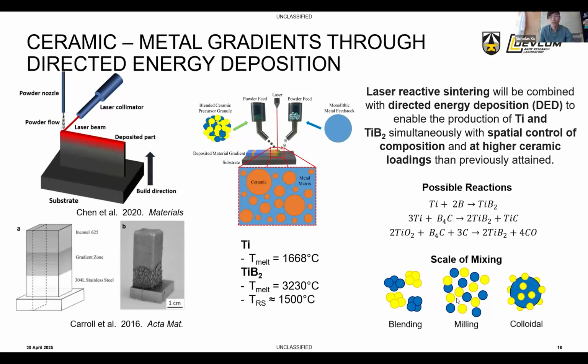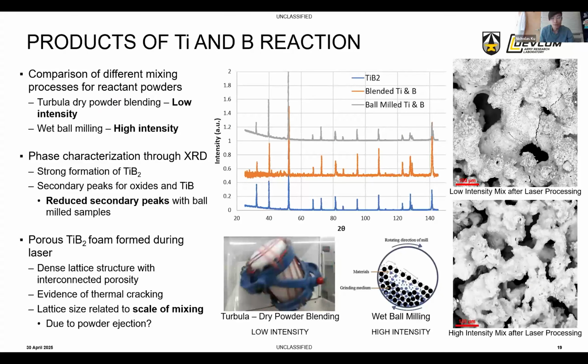One of the things that we're trying to figure out is how ceramic materials potentially react under a laser system. In this project, we were looking at using precursors, titanium and boron, which under a laser reacted to form titanium diboride, an advanced ceramic that we have some interest in. We did a lot of work on understanding how well you need to mix the titanium and boron, in micron down to nanoscale powders, with different mixing intensities, and then looked at different laser parameters to see how they affected the density of the part, how the phases formed, the microstructure, and things like that.